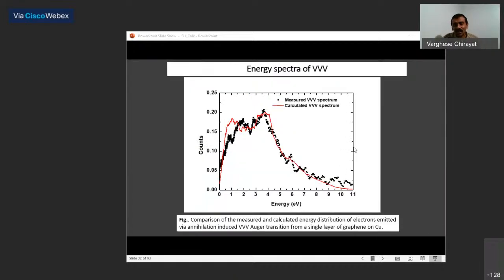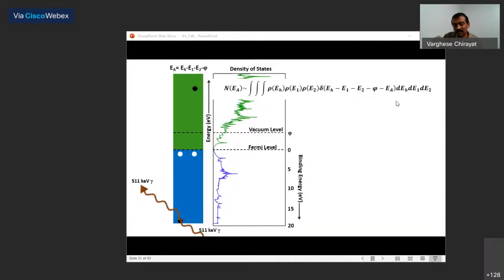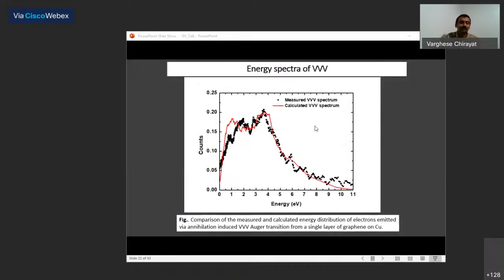And fortunately for us, what we thought was a VVV process was a VVV process. So the black is the experimentally measured spectra, and the red is the spectra which is just calculated using the convolution of the density of states that I have shown here, or the integration over the density of states I have shown here. And since we also calculated the spectra, we also calculated the probability for a hole in the valence band to decay via this process. And we found that the Auger decay probability is 1. That means almost 100% of the time, if you create a hole deep enough in graphene, it is going to decay via an Auger electron emission.